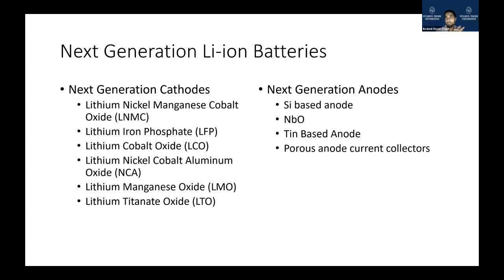So what is actually happening? You are inserting lithium faster inside this anode. And if your anode is capable of this high insertion, you are actually making it a fast charging battery. So niobium oxide is a very good candidate for this type of fast charging battery, because niobium oxide can charge the battery 5 times faster than carbon anode. So if you use niobium oxide, then your battery will be much more fast charging than the traditional graphite anode.